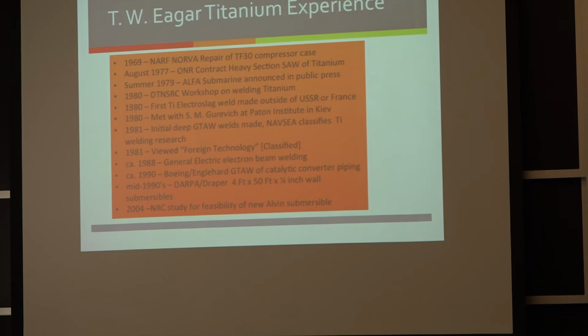I came back, and in the room 2 doors down, we made the first Electro Slag weld outside of the Soviet Union or France. They made one in France. And it looked absolutely terrible. But it deposited metal and it didn't use much flux. The problem with the submerged arc process was it was using 8 pounds of flux for every 1 pound of titanium, and the flux was costing $100 a pound. I determined this was uneconomical. I actually did a mathematical model to show how uneconomical it was compared to steel.